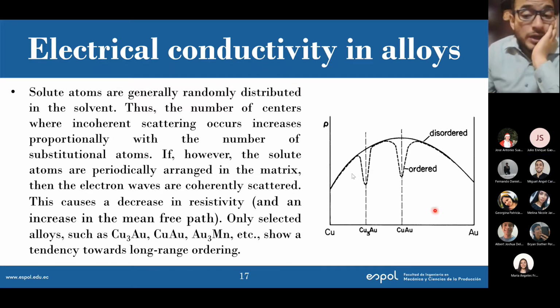Yes, actually. I mean, if you anneal the material slightly below the order disorder transition temperature, because alloys that present this order disorder behavior have a transition temperature. If you anneal slightly below that temperature, then you will get an ordered state. And obviously, that annealing has to be accompanied with moderate cooling. Whereas if you quench the material, so you do a rapid cooling, then obviously you will get a disordered state, right? So it's related to how you heat treat the alloy. Perfect. Okay.